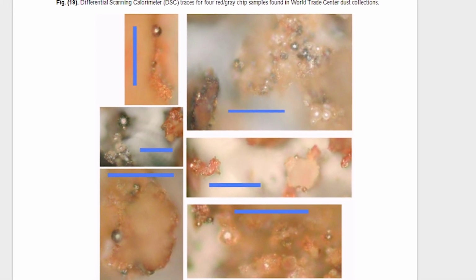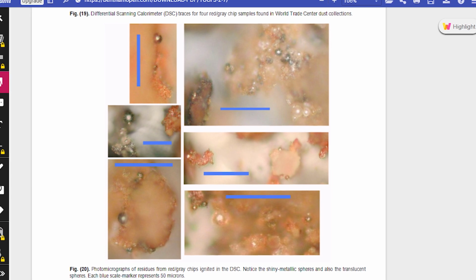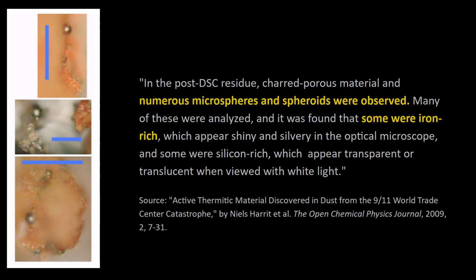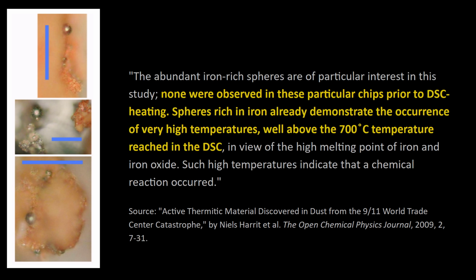Is he okay? They then argue that the almost literal smoking gun is the formation of iron microspheres after the chips are heated. Quote, "In the post-DSC residue, charred porous material and numerous microspheres and spheroids were observed. Many of these were analyzed, and it was found that some were iron-rich, which appear shiny and silvery in the optical microscope, and some were silicon-rich, which appear transparent or translucent when viewed with white light. The abundant iron-rich spheres are of particular interest in the study. None were observed in these particular chips prior to DSC heating.